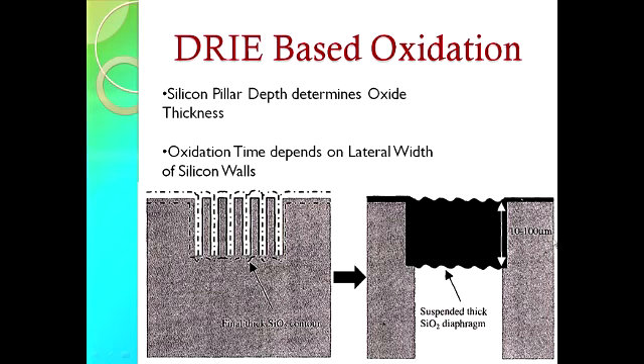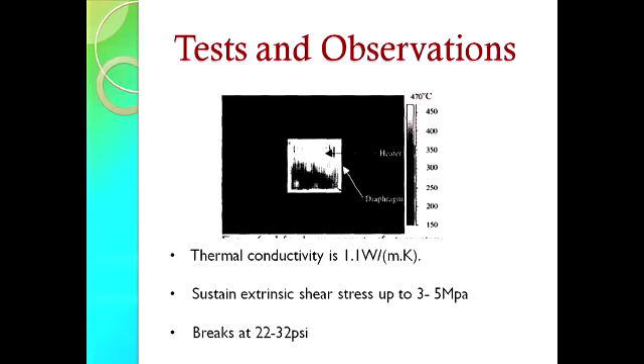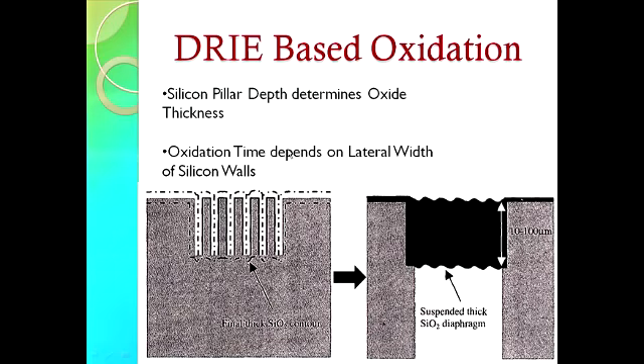It's like a pattern, like we can form. For example, so you form the pattern, you oxidize. Do you etch away what was that pattern, or that pattern becomes the oxide? So here we use a silicon ring, which means we want only the silicon ring, like only this portion. I see. So in order to get that, we can etch away this portion, and we can form a silicon ring. Now. Thank you.